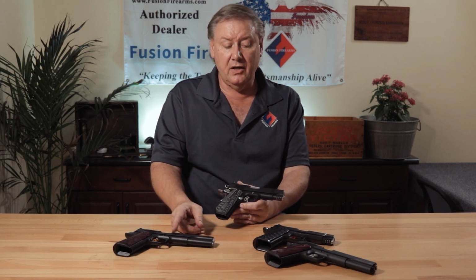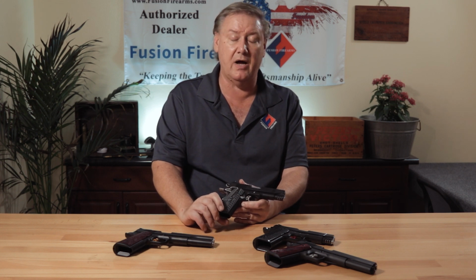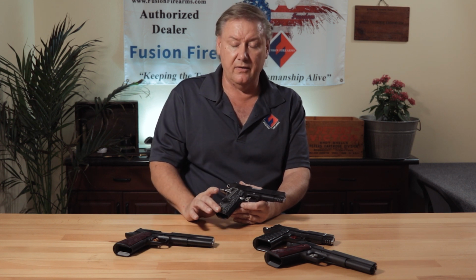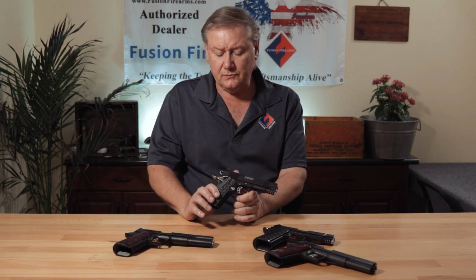Now, with the Ion Bond DLC, you can do a high polish and try to do the Ion Bond. The issue I have run into with trying to do high polishes with DLC is we usually have to redo it 3 or 4 times before it gets to my standard, because you'll have little spots, little inconsistencies. Any particles that are floating around that vacuum chamber get adhered to your beautiful polished surface, and it doesn't look very good. You have some spots. So again, I don't really recommend anything but the matte finish for the DLC or the Nitro Carburizing.